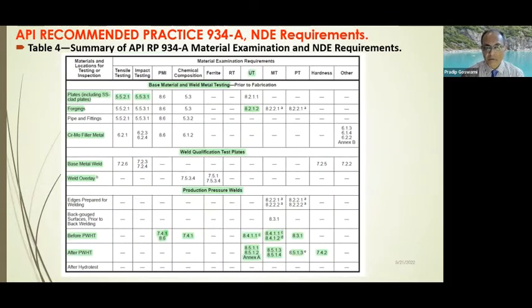And this is a quick summary of the testing required. As you can see here, this table is taken out from the same RP 934A. You see here, weld procedure, you start with the base material. You see the plate, forging, piping, right? You have everything: tensile, impact, PMI, then chemical composition, RT, UT, as well as any test you talk about. They are needed for the raw materials, for the plate materials as well as forging, piping and other components. When you talk about the welding consumable, you require tensile, impact, PMI, chemical composition, and you need the step cooling test also.